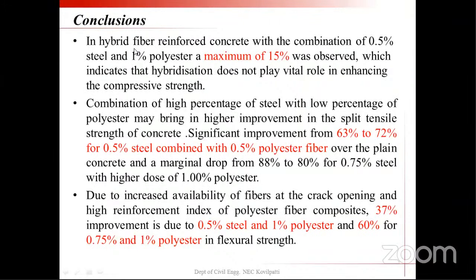So the overall conclusion is compressive strength has been improved up to 15% with the combination of 0.5 and 1% polyester. In the case of split tensile strength, a significant improvement is observed in the range of 63 to 72 for the 0.5 steel and 0.5 polyester combinations. And a marginal, small drop is also observed from 88 to 80 for 0.75 because of the excess dosage of 1% polyester fiber series. And flexibility has been improved up to 37% with the inclusion of 0.5 steel and 1% polyester, and 60% for 0.75 and 1% polyester.